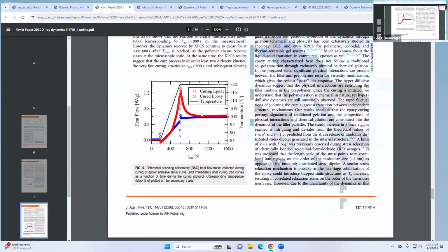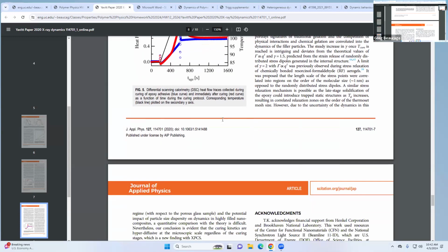Okay, so this is another one. We looked at this reaction under DSC, differential scanning calorimetry. This is another way to track these kinds of reactions because they give off heat as they go through that reaction state. So we put our sample through the exact same heating protocol in DSC, and we saw that the heat flow followed that increase and then that decay as well after we hit the curing process. So the thermal properties of this reaction seem to correlate very nicely with the nanoscale physical dynamics of this reaction as well. And the blue one is just showing a scan we did right after it's cured, once the whole thing has been eaten up. Those are just the natural heat flow changes in the material.